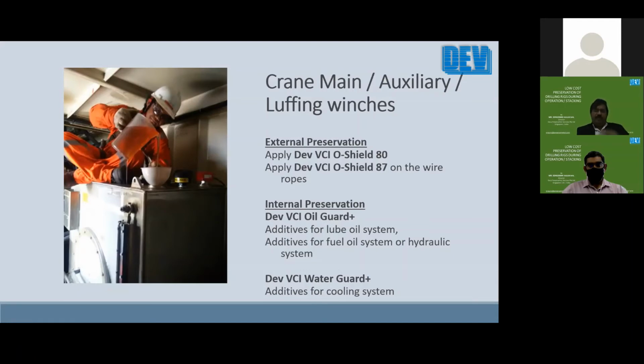You know, all these tanks have breather valves, so moisture can get in and out due to the temperature variations during the day and night. The moisture inside condenses and forms a water pool at the bottom of the oil tank, and the top aerated surface is exposed to the moisture-laden air. So both the water below the oil and the tank surface above the oil can be taken care of by this oil guard additive by forming a protective film on the metal surfaces, above the oil film, between the oil and the metal tank, and also between the water and the metal tank. As a result, the tank and the parts are completely protected.